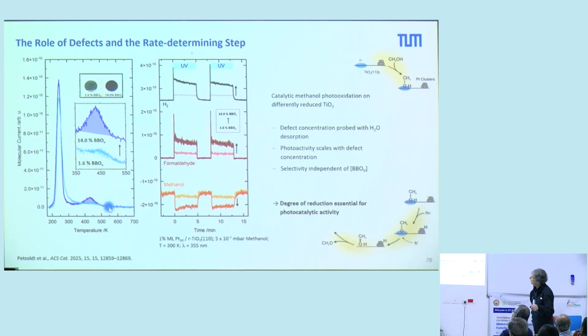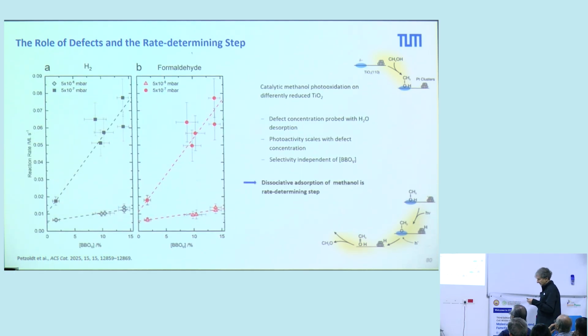Now you see the influence on the photoreactivity. And you see that if you have a high density of BBO sites, you have a high reactivity because you have more reactive sites. If you decrease the BBO sites, you have here a lower reactivity. That means the BBO sites are indeed relevant for this photocatalytic process. And you can measure the reactivity as a function of the density of BBO sites, and you see a linear behavior. It's a quasi-first order process.